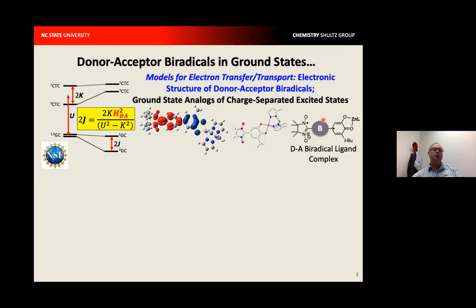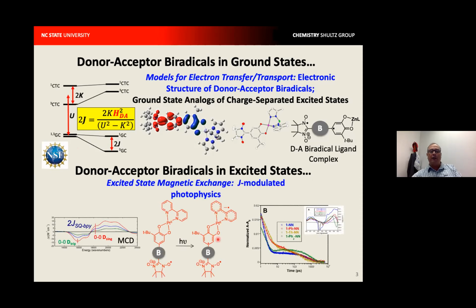And so we've used that most recently to evaluate any physical measurable quantity that's directly proportional to the electronic coupling matrix element. And I'll show you an example of that in just a minute or two. And so more recently, we're generating these donor acceptor biradicals in excited states by photoinduced electron transfer using these typically platinum or palladium complexes that are square planar d8 metal ion configurations. And the square planarity, and with the assistance of a particular d orbital, there is sort of a pi pathway that connects the catecholate, now donor, with the diimine acceptor.